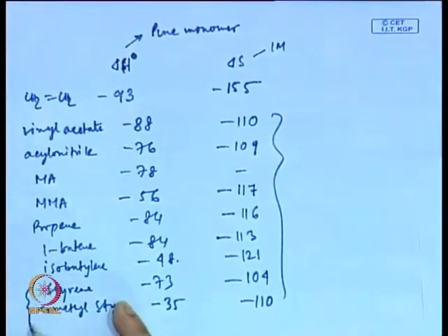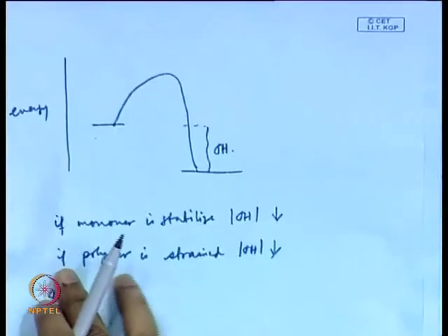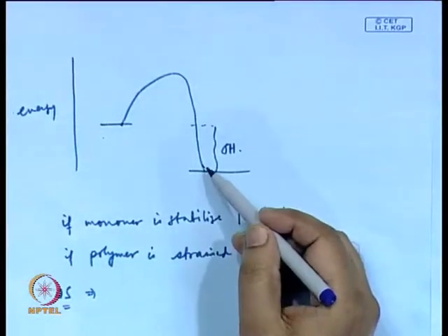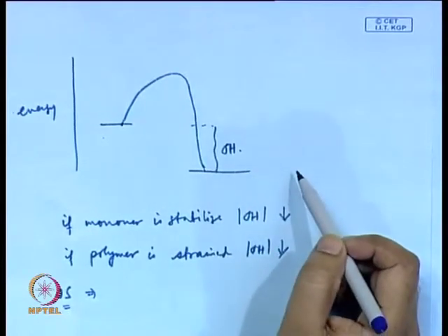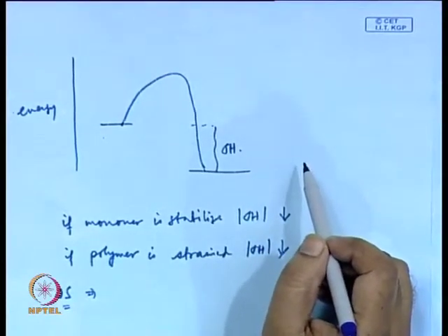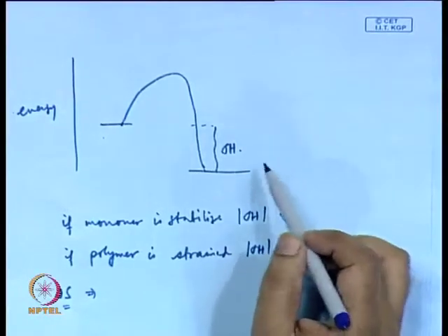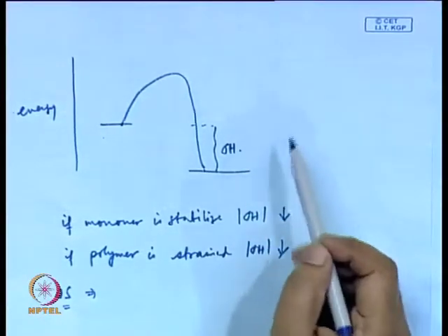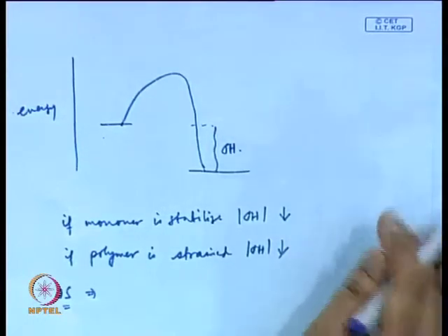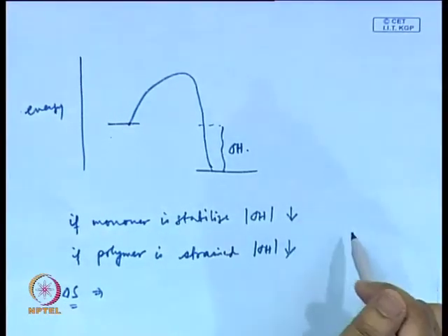Now, let us compare between first styrene and alpha methyl styrene. Obviously, this alpha methyl styrene have a much lower DelH value. Now, that is because this polymer made from this 1,1 substituted alkenes are going to generate, when this pi bond is sp2 is converted to sp3, they are going to give lot of strain.